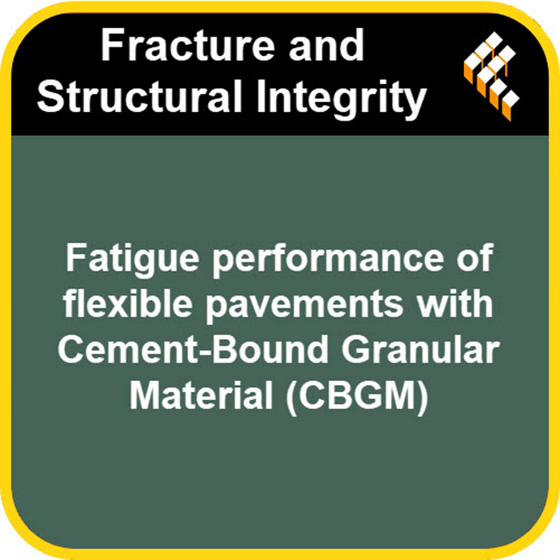Wow. Instantaneous failure. That sounds pretty dire. I imagine that's not a call an engineer wants to get from the construction site on day one. Boss, the road cracked already. It's certainly not ideal, and it's especially striking when you compare it directly to the De Beer criterion results for the exact same configurations. For those same types 1, 2, and 3, De Beer predicted fatigue lives ranging from 143,000 repetitions up to over 1 million load repetitions. 1 million compared to instantaneous failure.